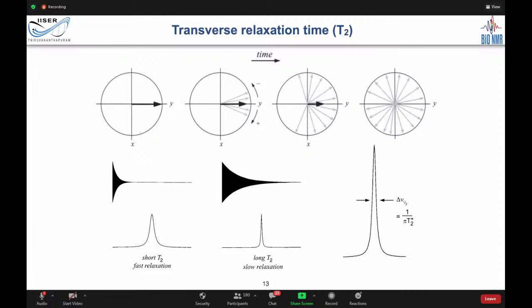And that is called spin relaxation because the spins are able to exchange energy between each other. So that is why it's called a spin relaxation time. And the line width of the spectrum depends exclusively on it. Why is that? Because this is much faster than T1. So the line width actually depends on your T2, the transverse relaxation time, 1/πT2.